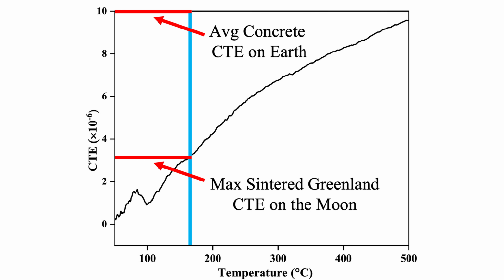We also ran an experiment for the coefficient of thermal expansion. This shows how much the material expands when it's exposed to heat. The CTE of concrete on Earth is 10 times 10 to the negative 6. The temperature range on the moon is negative 255 to around 165 degrees Celsius. The CTE of the sintered regolith at this temperature range is around 3 times 10 to the negative 6. This shows that the sintered material is thermally stable enough to be used as a construction material on the moon.